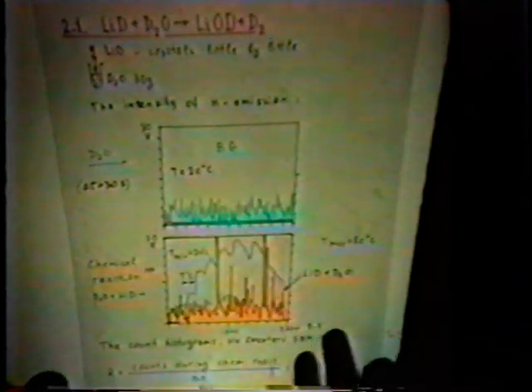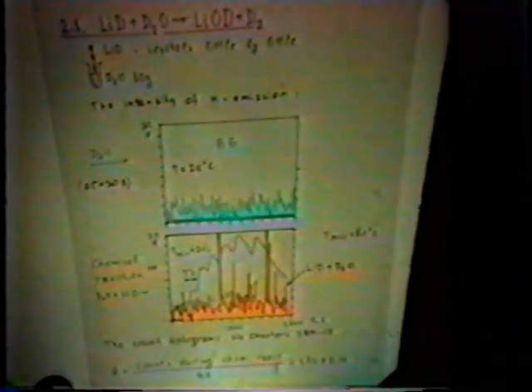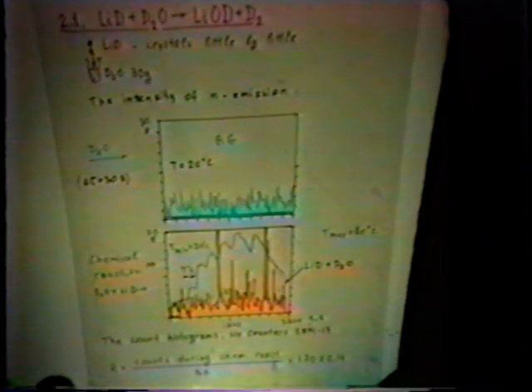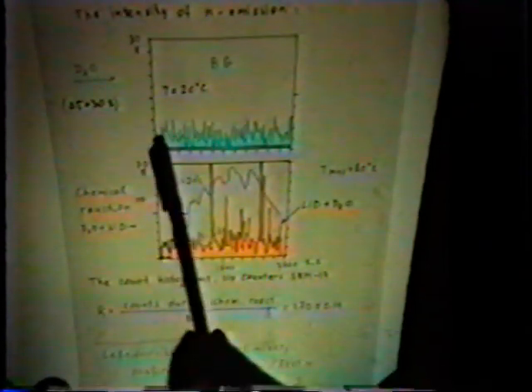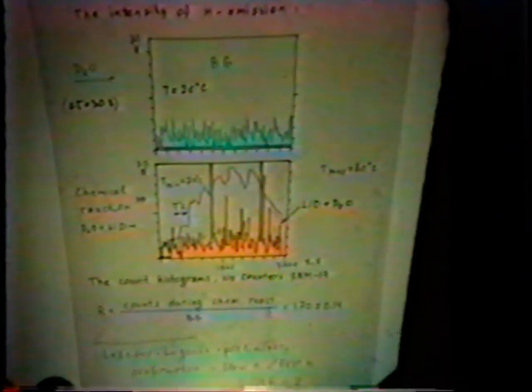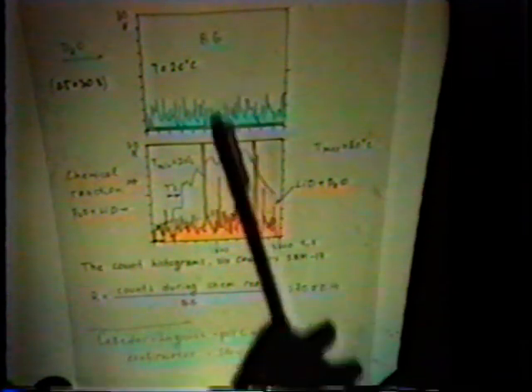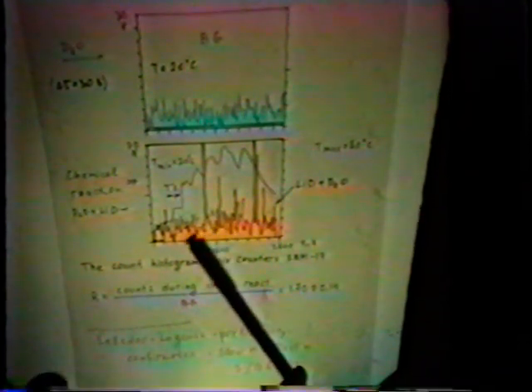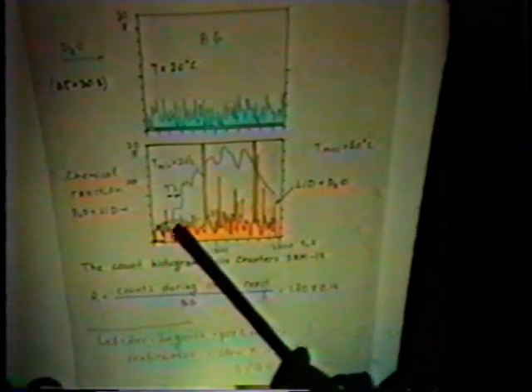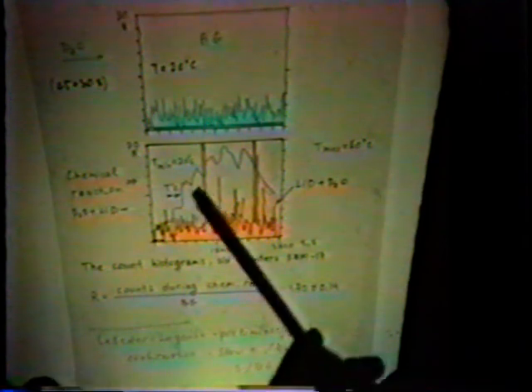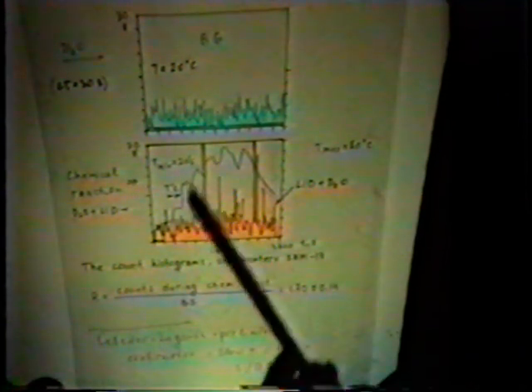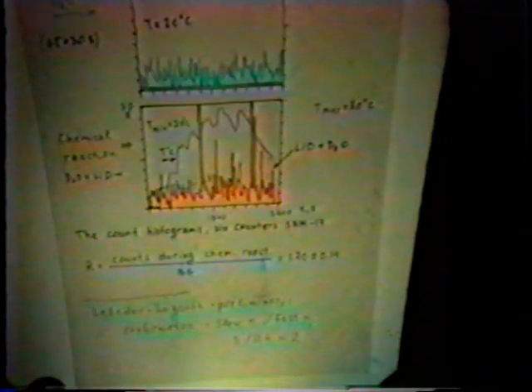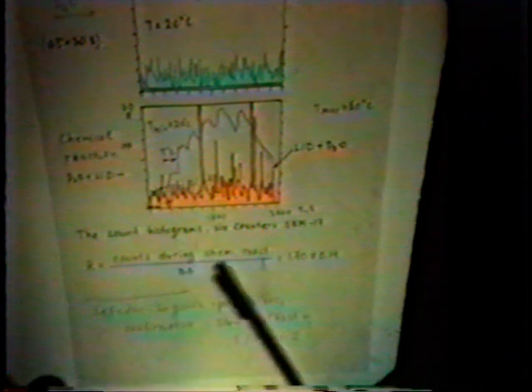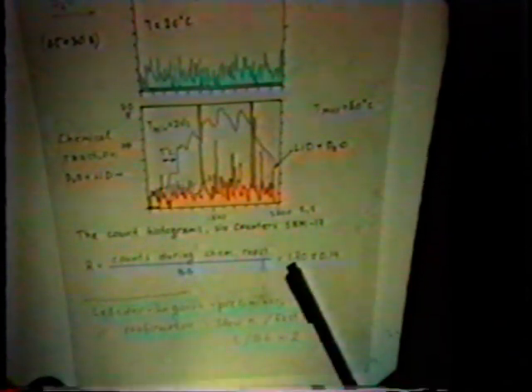They used 2 different kinds of chemical reactions. First is the following one, and about 30 grams of heavy water were placed inside of a test tube, and lithium D crystals were added little by little, and they measured the intensity of neutron emission. Here you can see results of measurement with just heavy water. This is the background level. And you can compare it with this picture, which displays the results taken during chemical reactions. The blue curve indicates the rise of temperature which is connected with chemical reactions. And this rise is correlated with neutron bursts. And the ratio of the number of counts during chemical reactions to the background level was about 1.7.